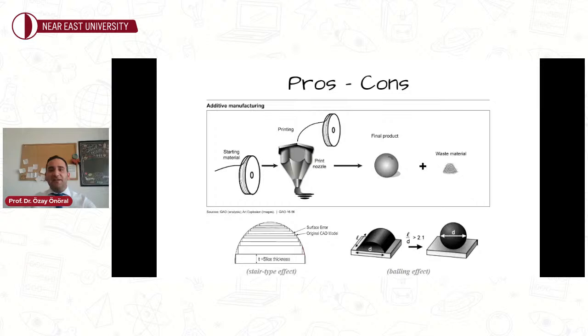It's a common failure in additive techniques. If I'm going to give the name of an additive technique specifically, I can say selective laser melting. We're going to discuss this topic later on, but the balling effect is a common failure, especially in selective laser melting. This phenomenon can increase surface roughness, reduce density, cause pores in the final product, and in severe cases even hinder the fabrication process. The balling effect occurs when the molten particles cannot wet the underlying material layer due to the surface tension, and it in turn separates the liquid particles, unfortunately. Several factors should be considered regarding this effect, like high scanning speeds combined with high laser output powers should result in less balling effect, for example.